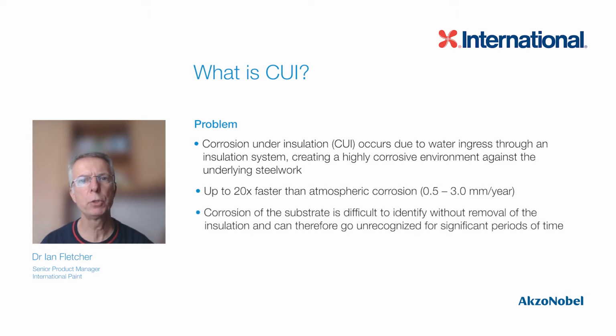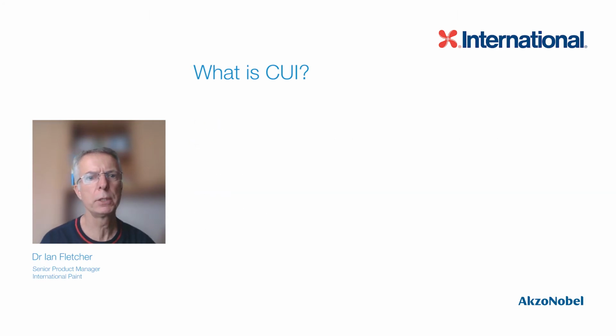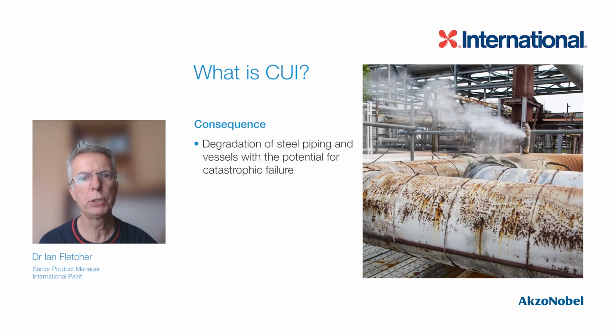Corrosion of the substrate is difficult to identify without the removal of the insulation and can therefore go unrecognized for significant periods of time. As a consequence, there is considerable degradation of steel piping and vessels with the potential for catastrophic failure, and this then leads to premature repair or replacement.